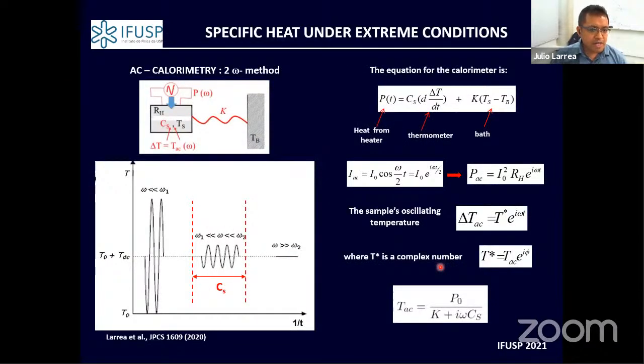So this is just a pictorial representation of the experiment. What we can see here is that our method consists of a measurement of the heat capacity of your sample, by applying a modulated heat on the sample and measuring the temperature difference of the sample. If you see here the steady-state equation of the system, consider that you can apply a modulated current, dissipated in a resistor here, right? The signal that you pick up will be at double the frequency that you apply as modulated heat. This is why we call it a second harmonic method, right?